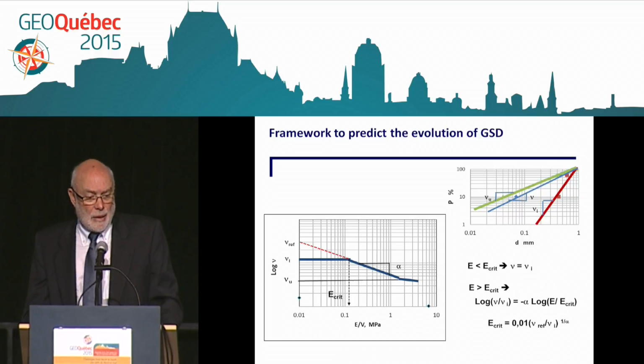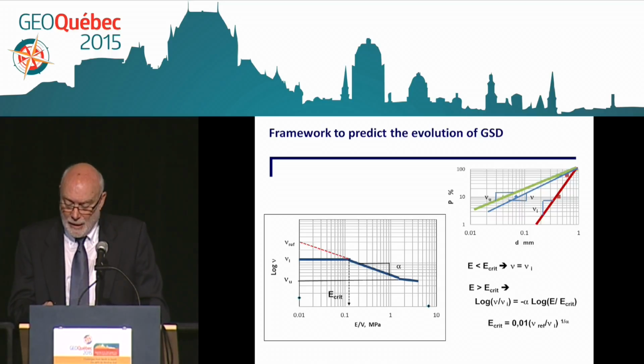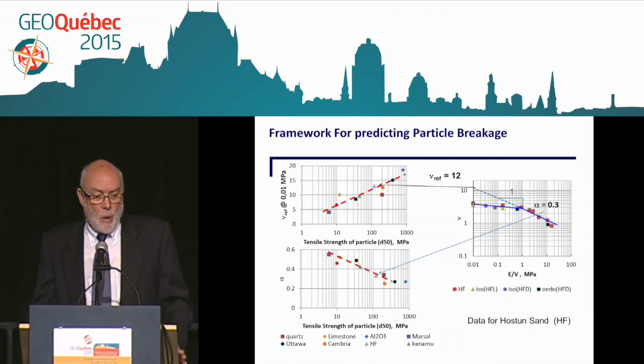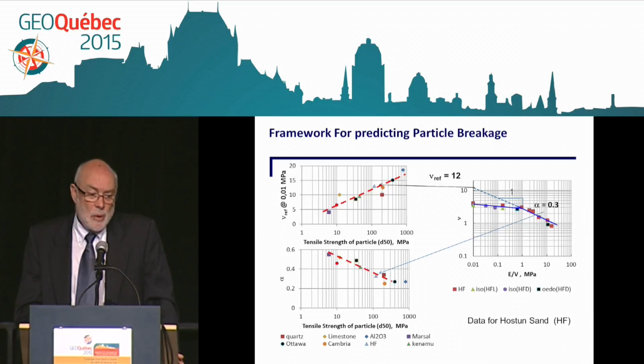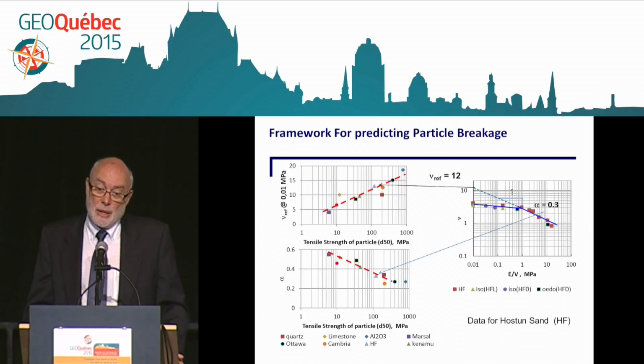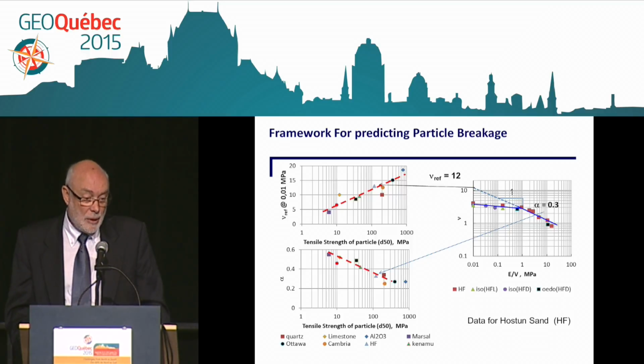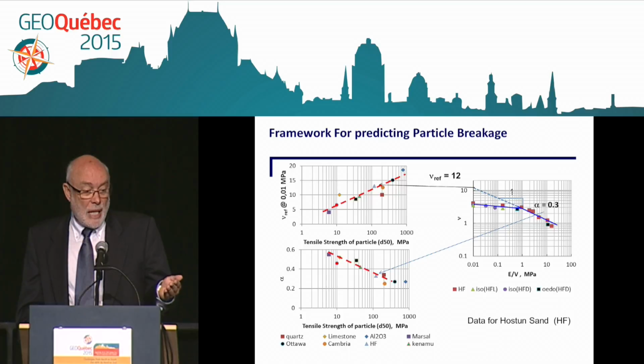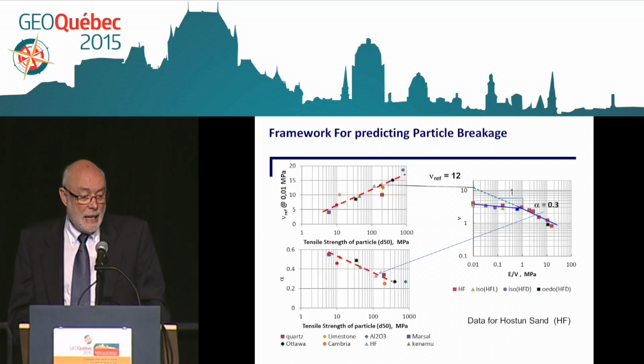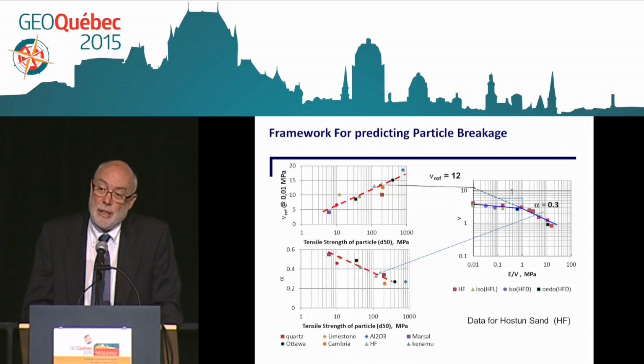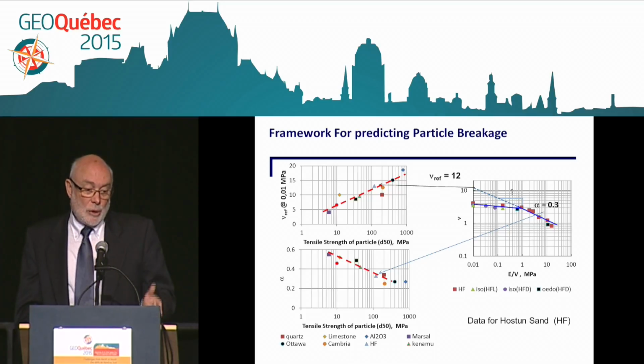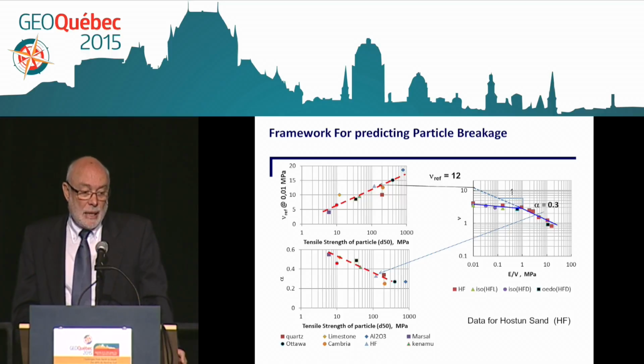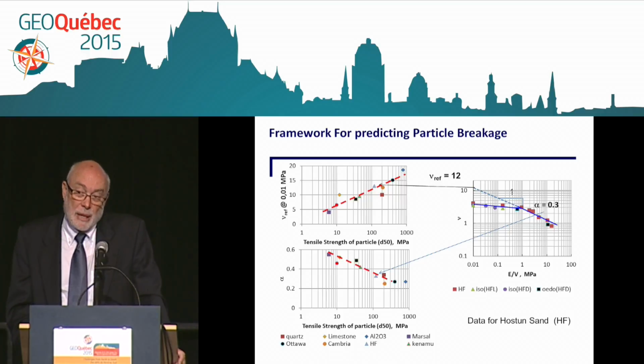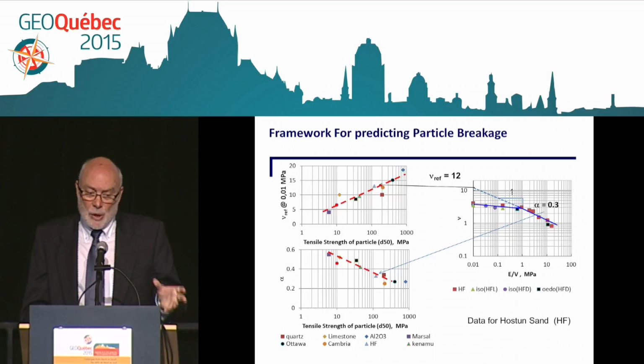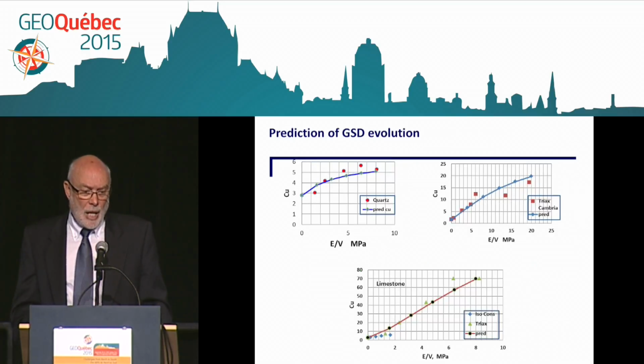It's an easy way to express this mathematically, and now we need to have the parameters to use. Again, we went to the literature and extracted all the data we could, and we see that the slope of that crushing line can be expressed as a function of the tensile strength of the particle. And also the position of the line has a relationship with respect to that same particle strength. So it's very consistent. And how does it predict?